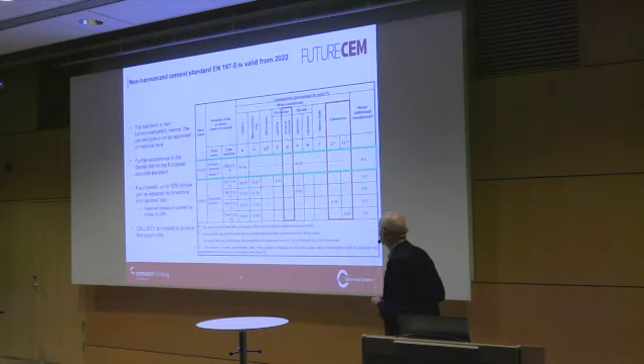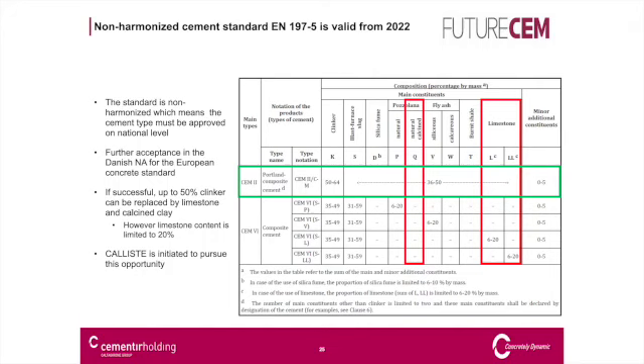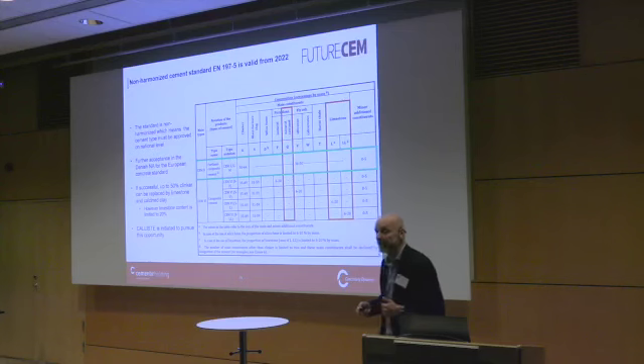Okay, what about the future? Now we have already heard about standards. One of the futures is a new standard, EN 197-5, which is not harmonized. And this is again this horrible argument between the European Commission and CEN, the standardization organization, which has more or less stopped harmonization of new standards. So this is a non-harmonized standard. But the interesting thing for the calcined clay limestone cement is that the new standard will enable us to increase the clinker replacement from 35 to 50%. So this is the opportunity we have.